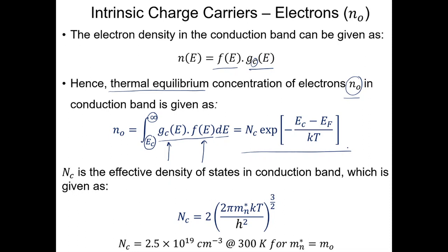However, keep in mind we have taken an approximation here. The f that you use for doing the integral is the Boltzmann approximation of the Fermi-Dirac function. The Maxwell-Boltzmann approximation of the Fermi-Dirac function will give you this relation, and going forward, as I also told you in the previous module, always remember the assumptions. Going forward, we will always assume this for easy maths.